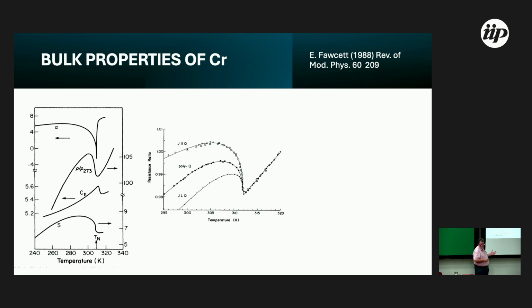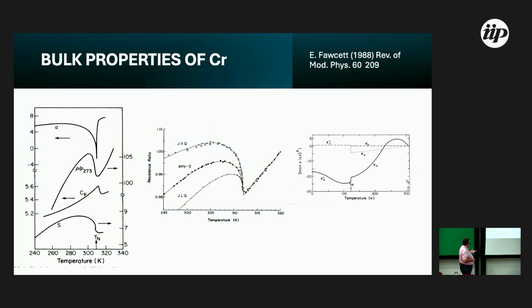10 Tesla, for example. 10 Tesla, 12 Tesla. And this behavior is change of magnetic domains in only one direction, for example, the 001 direction of the chromium. Okay? And observing the resistivity dependence on the Q state preparation. And this measure of the strain, for example, observe of the Néel transition at 311 K and 120 K, the spin flip transition. What's observed is strain, because the change of magnetic phase changes the lattice parameter. This effect is observed.